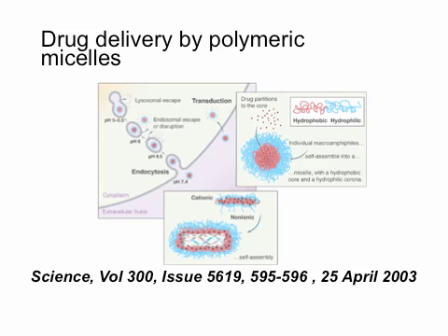So you have the drug in the micelle, but you also have a tiny bit of drug in the water. Temperature fluctuations make the water phase oversaturate a little bit. As a result, you could get crystal formation in the water that sucks empty basically everything in the micelle. So the end result would be a lot of large crystals of your drug on the side of your storage bottle. That's not very practical anymore. So you need to find a more creative solution than that.